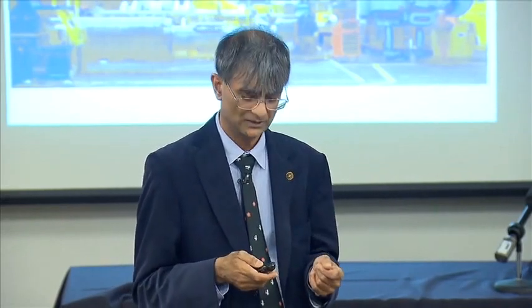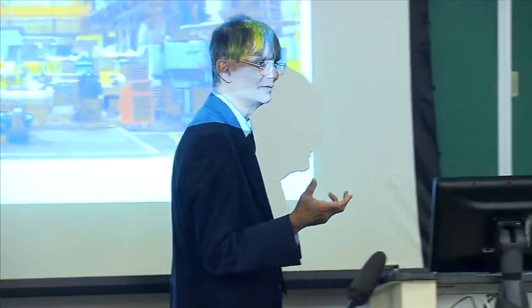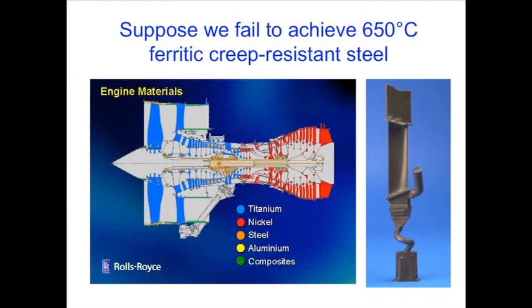And if you use an austenitic steel, you can get there, but the thermal expansion coefficient of austenite is too large. It causes thermal fatigue and other problems. So what do we do? Well, we have creep-resistant materials which are used in aircraft engines at 1400 degrees centigrade. These blades here are nickel-based, single crystal blades, and they are used in an environment at 1400 degrees centigrade, rotating at 25,000 RPM.